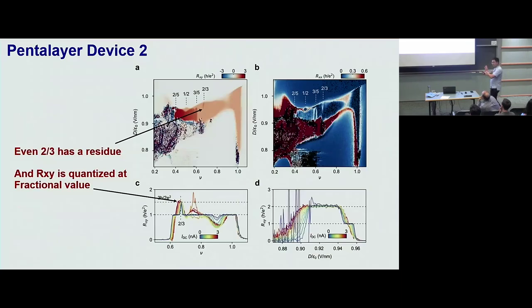It's a very similar twist angle. It's actually on the same chip. I call it pentalayer device 2. If I just show this big phase diagram here, it really mimics what I showed you in device 1, where they have big patches that have uniform color of Rxy and vanishing Rxx. However, in this device, you can see 2/3 actually has a little residue there. It's not completely gone as in the other device. And you still have the local dip at 2/3 in the Rxx channel.